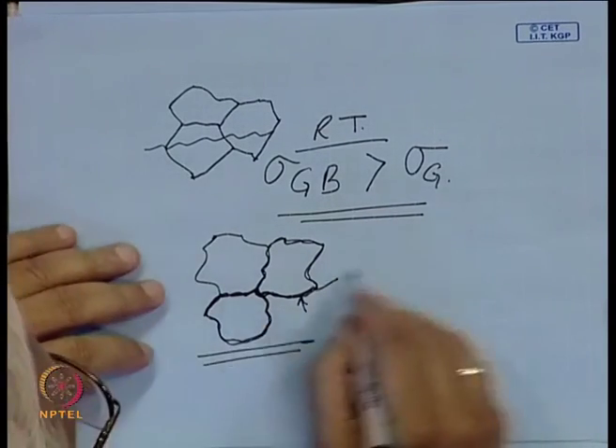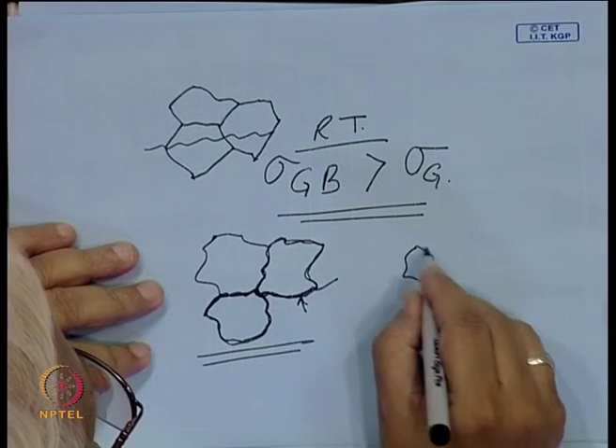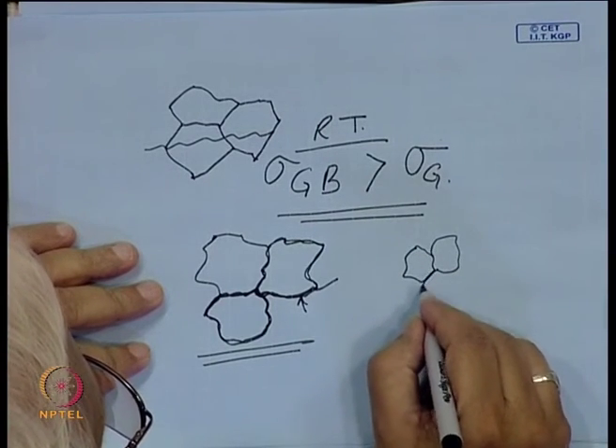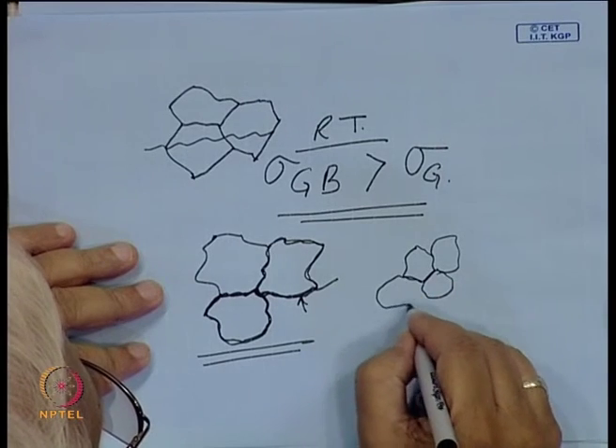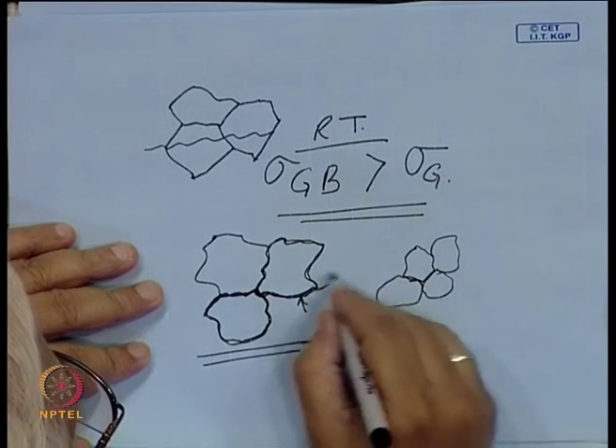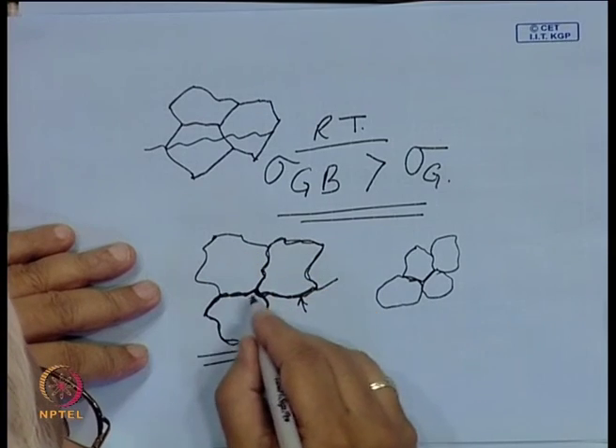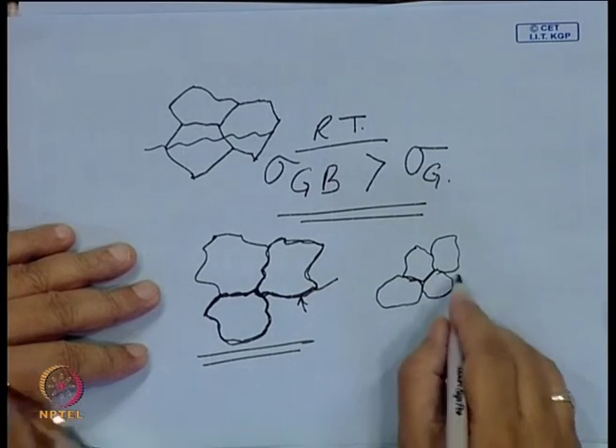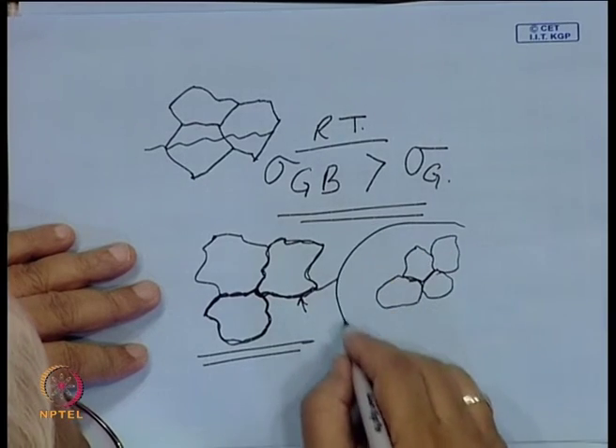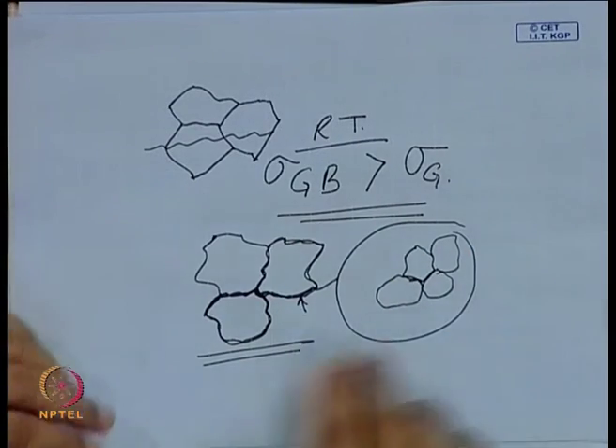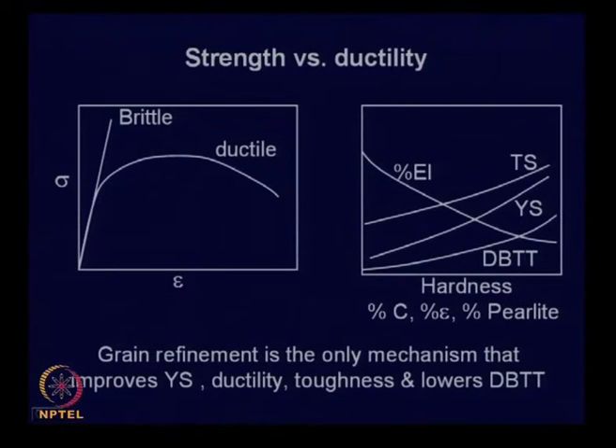Now, what happens if you make these grains finer? You reduce the chance of this segregation because you have more grain boundary area, so the chance of this kind of brittle network forming is reduced. This is one reason which makes fine grain steel more resistant to crack growth. So this is a mechanism which helps improve the strength without sacrificing ductility or toughness.